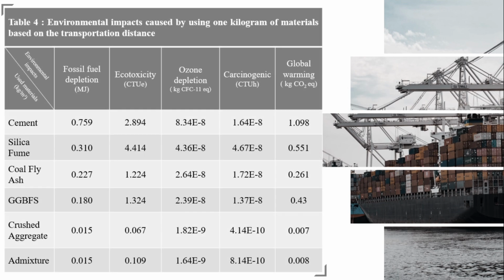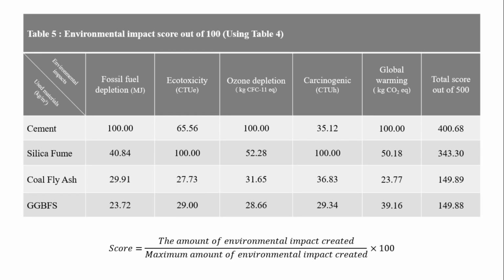After applying the transportation distances and material specifications in the Ecoconcrete calculation tool, the environmental impacts of each material were calculated by placing 1 kilogram of each material into the tool. This table provides the basis for comparing the environmental impacts of different materials. Since only SCMs can replace cement, a scoring system of 100 was applied to 4 materials: cement, silica fume, fly ash, and slag. As can be seen, the results show that cement and silica fume have the highest environmental impacts, while slag and fly ash have the lowest impacts.